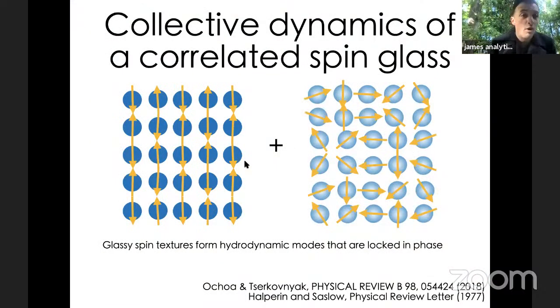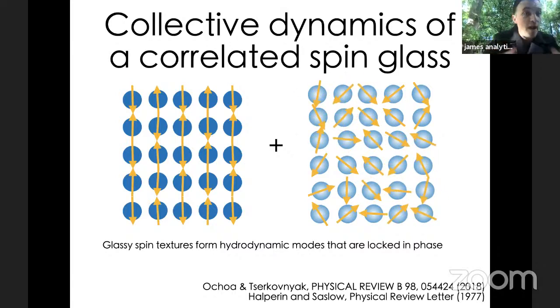Well, we think it connects to the first part of my discussion, which is the role of having a coexisting collective spin texture. What happens when you have an antiferromagnet that's stiff in itself and has its own well-defined equilibrium states, coexisting with a spin glass that doesn't have an equilibrium state in the same sense, but it does have collective behavior? And so the idea is that when we apply the spin polarized current, we're not just imparting angular momentum directly to the antiferromagnet, but we're actually imparting it to the spin glass as well. And because the spin glass texture is there, it's opening up another channel with which you can transport angular momentum onto the antiferromagnet. And that's perhaps why the efficacy of the spin transport grows as soon as the spin glass is frozen, as soon as stiffness for the spin glass sets in.